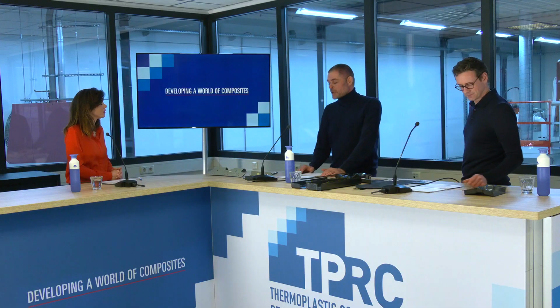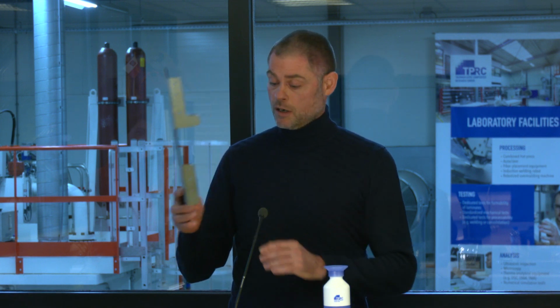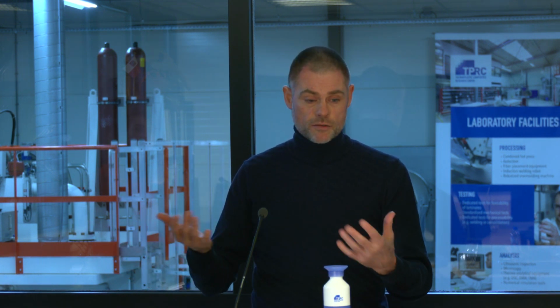Well, what do you need to further develop stamp forming, Sebastian Wijskamp? Yeah, so the majority of the parts flying at the moment are based on fabric reinforced composites. So we've got some examples here. These are clips connecting frames to a fuselage, for example. And we like fabrics, and they're like the cloth of your clothes, very coherent. When you have this molten blank at 400 degrees Celsius, it tends to sag. But due to the coherency of the fabric, you maintain the structure. You can almost throw the blank onto the mold with your pizza shovel. So it's quite easy, we like it.